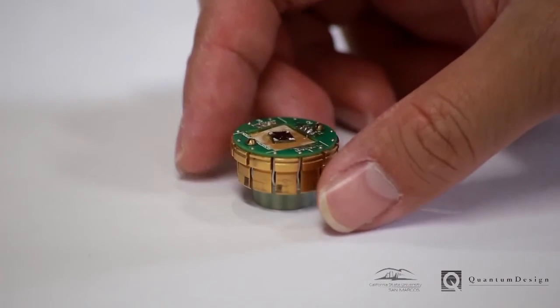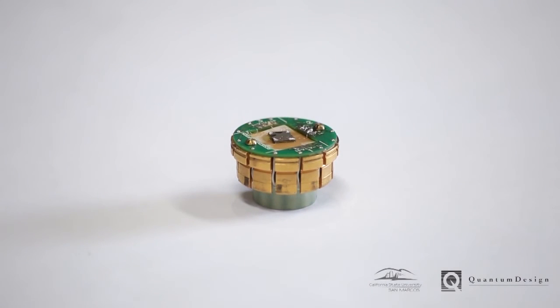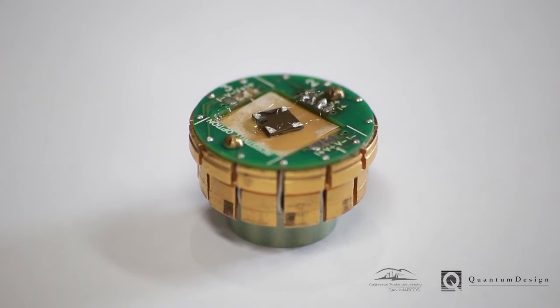In order to demonstrate the use of the magnetic field, we will now measure the Hall effect in p-type germanium. The Hall effect is the phenomenon whereby the current traveling through the material will be deflected by the applied magnetic field, resulting in a measurable Hall voltage. The sign of the reading will indicate whether the dominant carriers are negative electrons or positive holes.